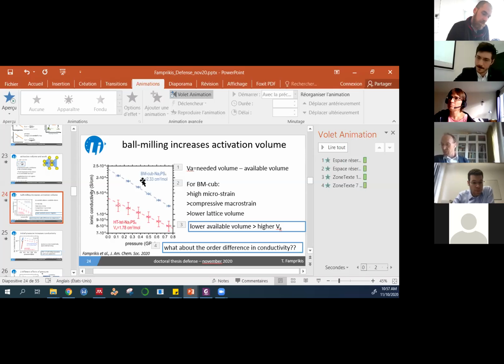I guess that's immediately also seen by the smaller lattice volume of the material. So then you would expect actually that the conductivity would be worse, right? It has to make more volume, but again, interestingly, leads to this local effects, like the ability to locally create volume for the diffusion. And this is a bit also why I thought maybe defects could be.